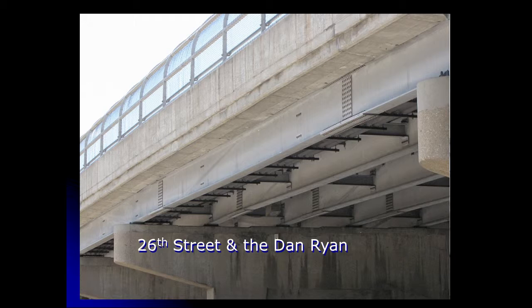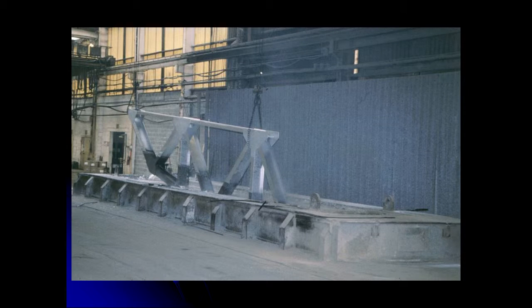We overlap at about 2 inches. So if you put a mil gauge here and a mil gauge there, you probably get anywhere between 9 to 11 mils. You put it in that progressive dip mark, there's about 13 or 14. Here's in the Truss Bridge, same thing, we're progressive dipping it.